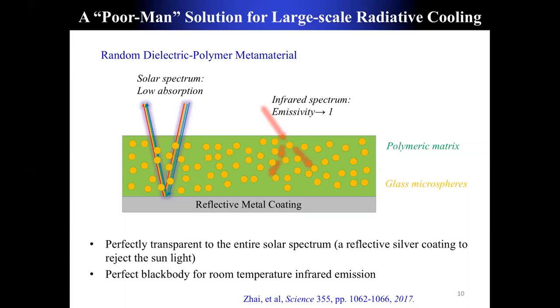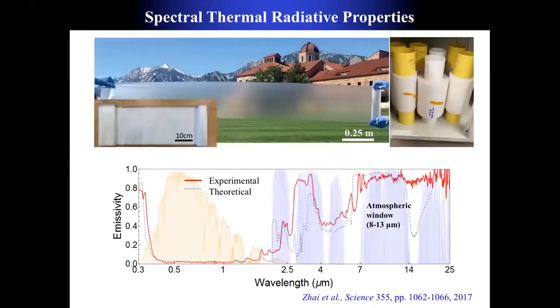One piece is polymer and glass microbeads, and this layer is transparent to sunlight and has high emissivity in the atmospheric window. In the meantime, there is a backup coating, a metal coating, which reflects sunlight. We made this material through roll-to-roll manufacturing. This slide shows that it's really transparent, but in the meantime, it scatters light, so it's diffusive.